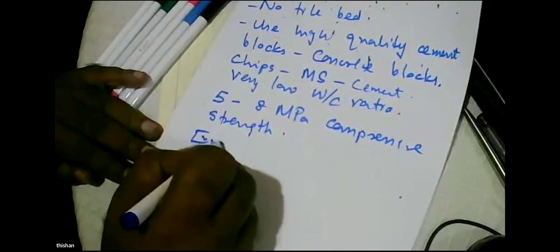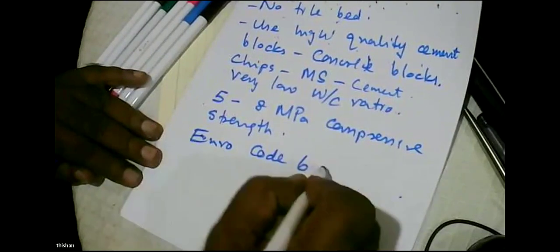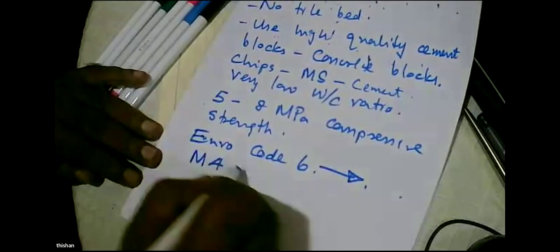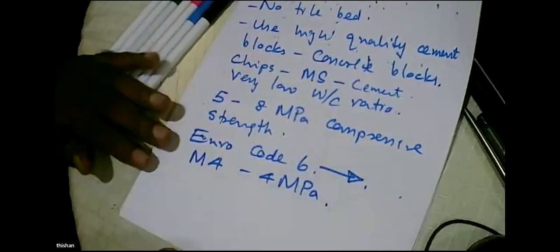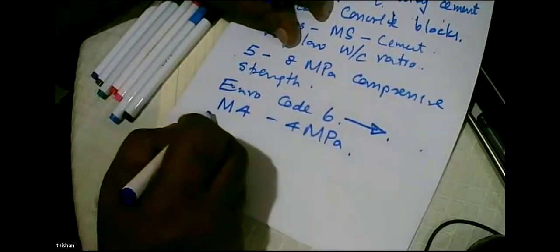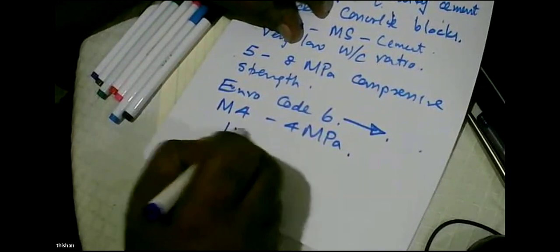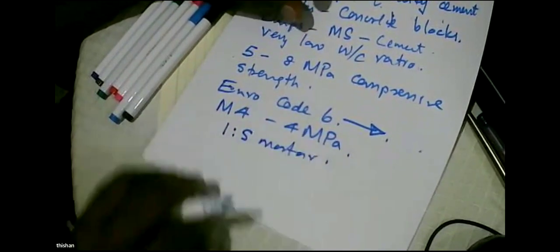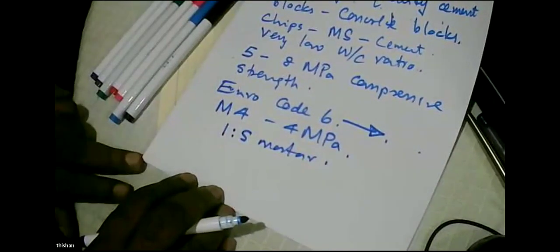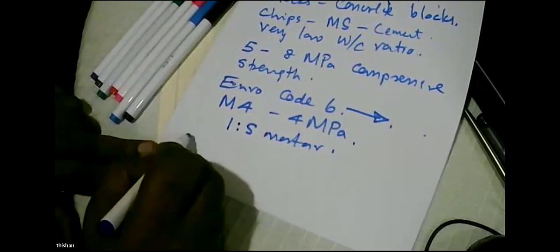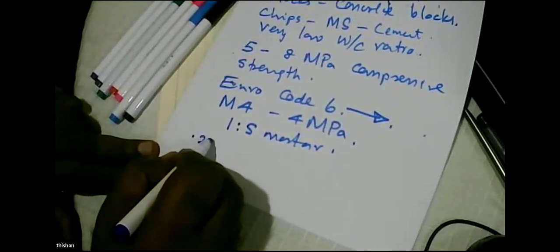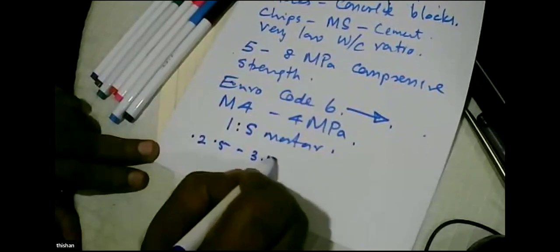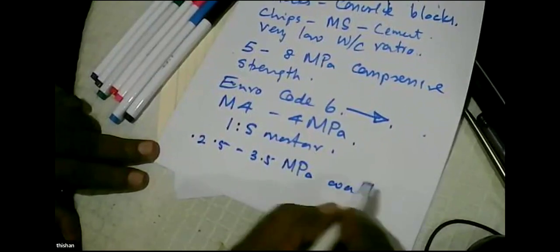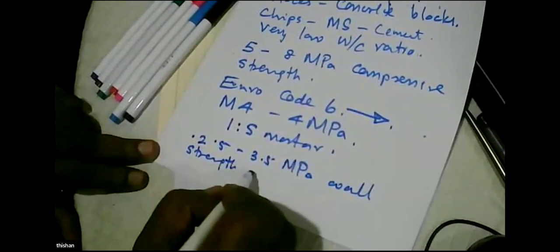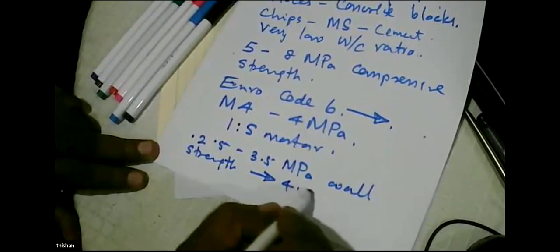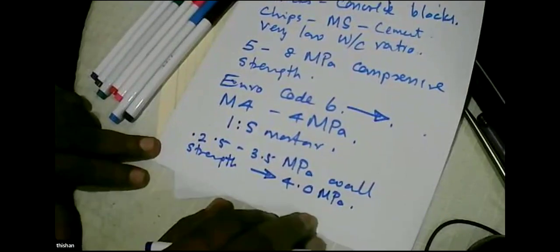And the Eurocode 6 tells us, with M4 mortar of 4 megapascal, when you know the block strength, M4 mortar is 1:5 mortar. With 5 to 8 megapascal compressive strength blocks, what happens? We get 2.5 to 3.5 megapascal wall strength, or you can even go for something like 4, depending on the strength of the blocks.